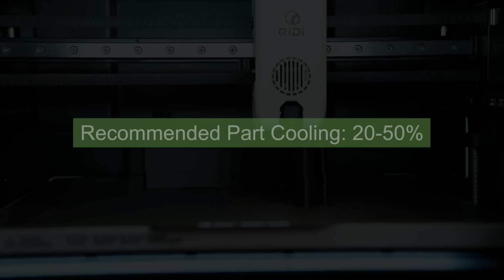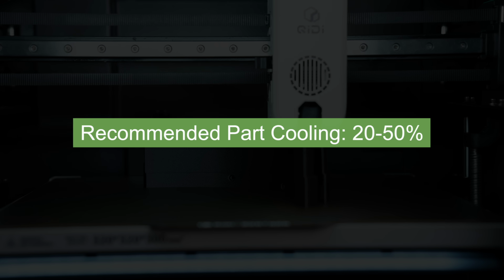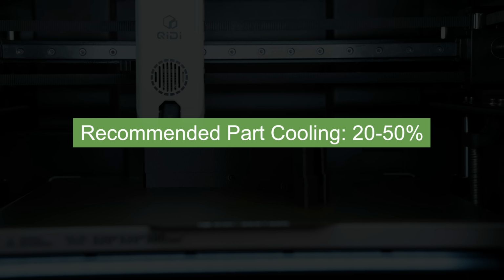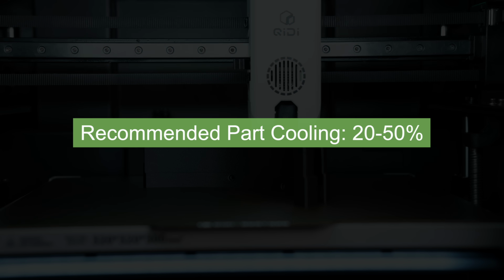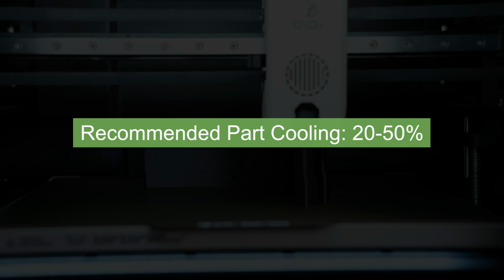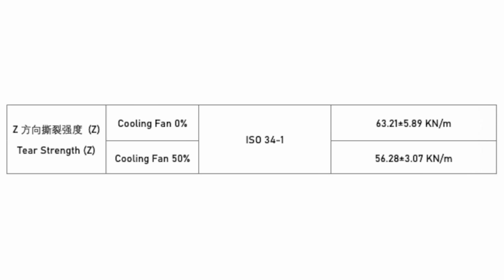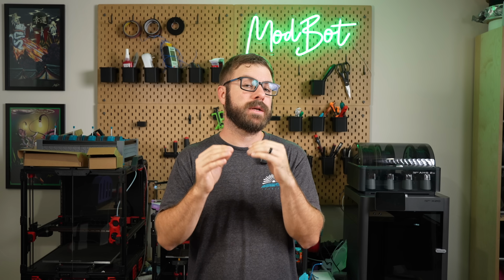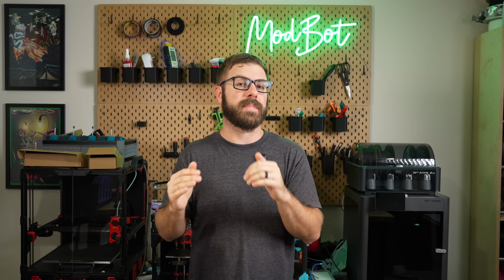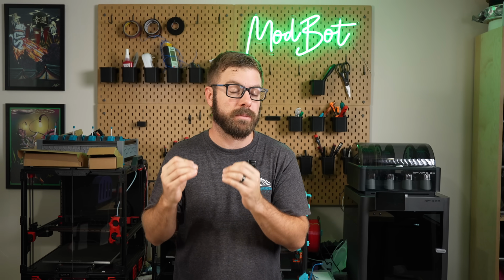For part cooling, they recommend between 20 to 50%, although that is something that you may want to adjust depending on what you're printing and what the specific application of that part is. QIDI's own testing shows a higher Z direction tear strength on the part printed with no cooling as compared to the one printed with 50% cooling. So if you're trying to maximize and get the absolute best interlayer adhesion, you may want to consider lowering or even turning off the part cooling.